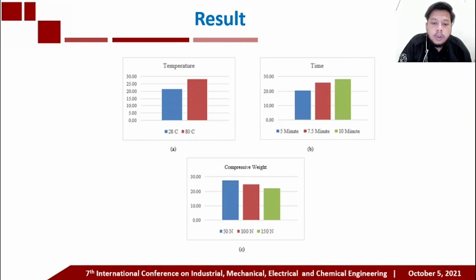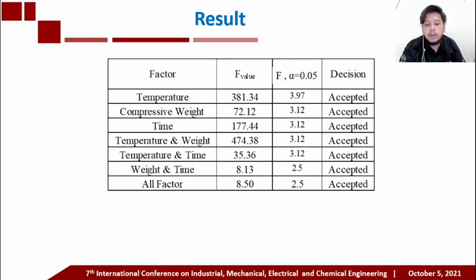From figure A, specimen with temperature 80 degrees Celsius is better than 28 degrees Celsius. Figure B, specimen with compressive time 10 minutes is better than specimen with compressive time 5 minutes and 7.5 minutes. From figure C, specimen with compressive weight 50 Newton is better than 100 Newton and 150 Newton. From the ANOVA test, it was found that all factors affect the tensile stress of the composite. The factor can be said significant or effective when F value is greater than F with alpha 0.05.